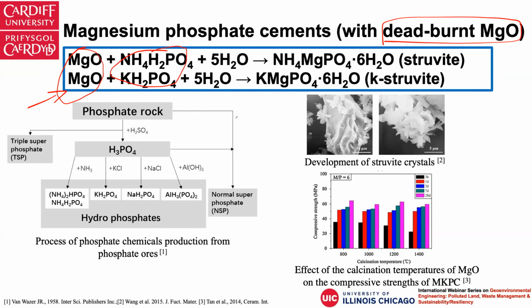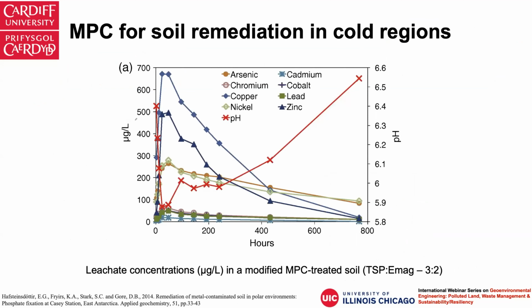But basically these magnesium phosphate cements are quite versatile. They can be used for rapid repairs. If you look at the compressive strengths, even using the dead burn magnesia, the compressive strengths can be as high as 35 megapascal in only 3 hours. So this cement is mainly used for rapid repairs and some very special applications. But today, of course, the topic is soil remediation.